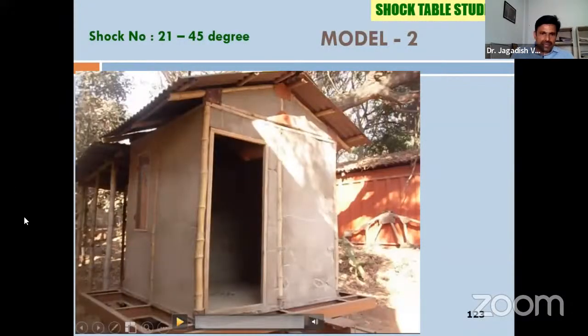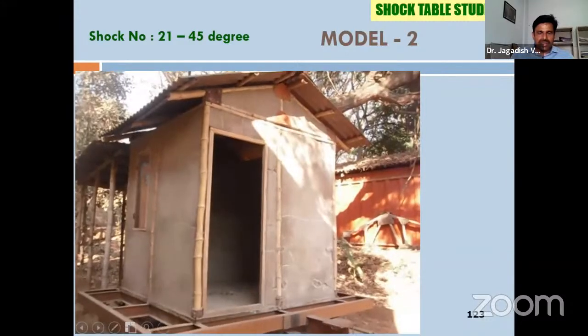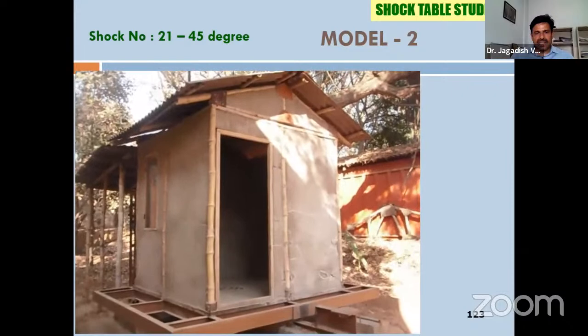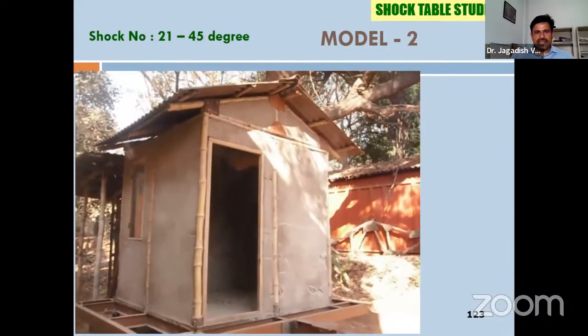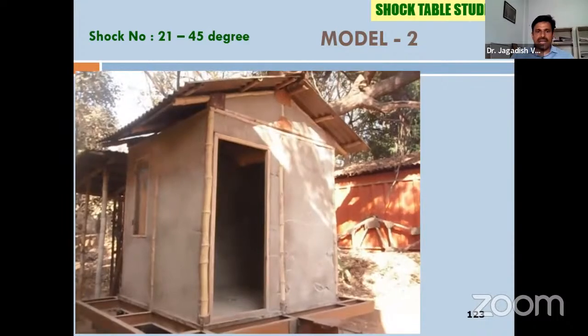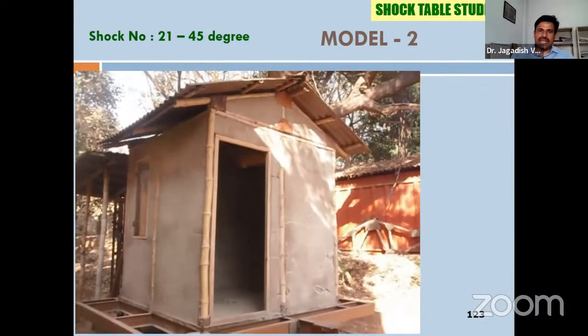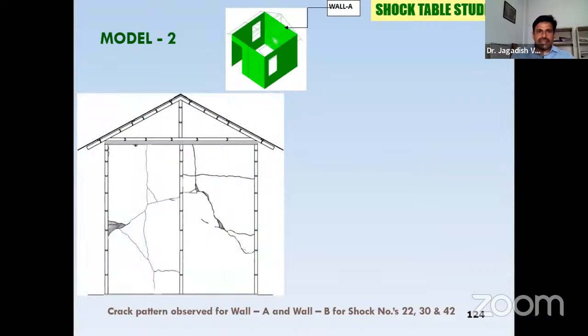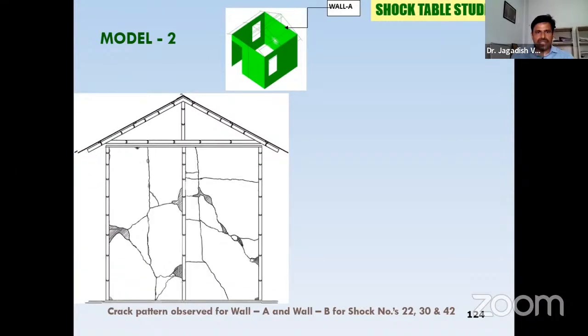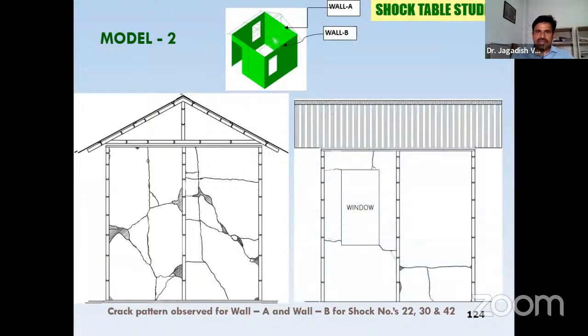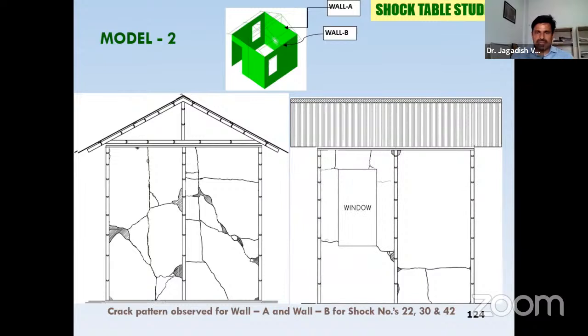You can see a typical video of shock number 21 at a 45 degree angle. The pendulum is released, hits the table, and then vibrates, and the crack progresses. These are the typical crack patterns observed for wall A and wall B. You can see here shock number 22, 30, 42. The cracks are getting wide open due to the number of shocks. You can see wall B also, with a widening of these cracks.